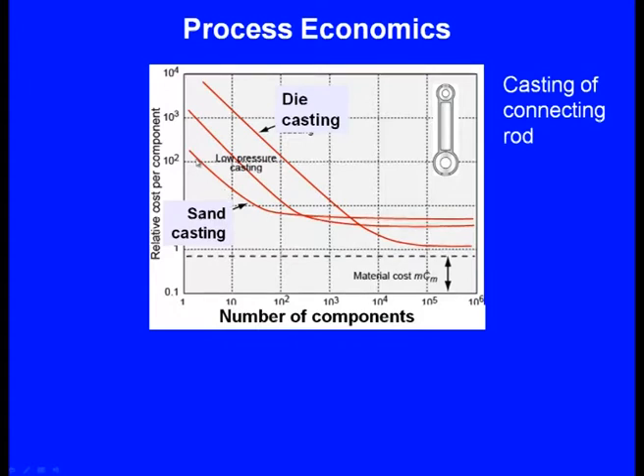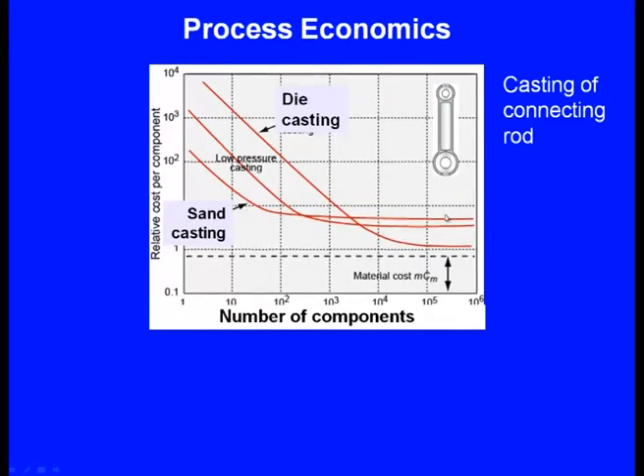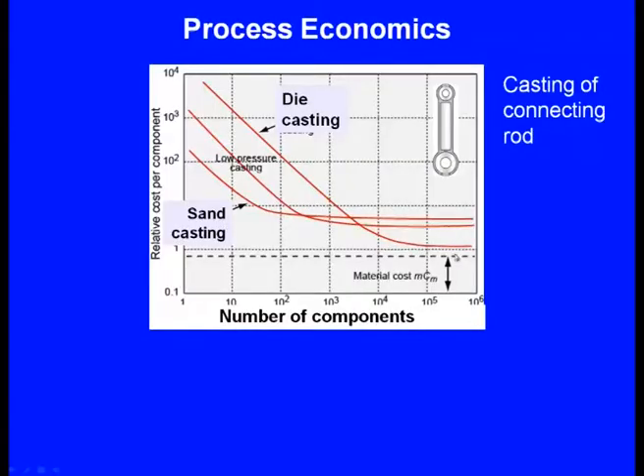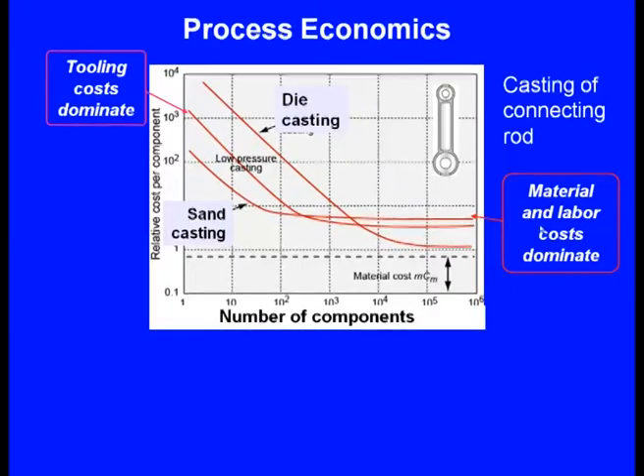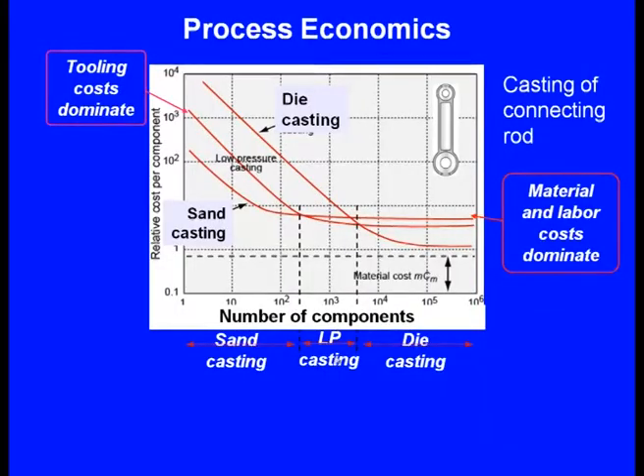For sand casting, even if few pieces are produced the cost is not very high, but as the number of pieces increases the cost decreases. Still, the cost of sand casting per product remains more than die casting per piece at high volumes. Tooling costs dominate in die casting, whereas material and labor costs dominate in sand casting. For low volume, sand castings are better; for intermediate volume, low-pressure die casting or die casting will be better.